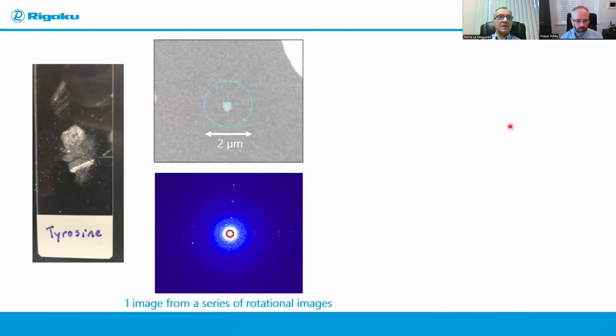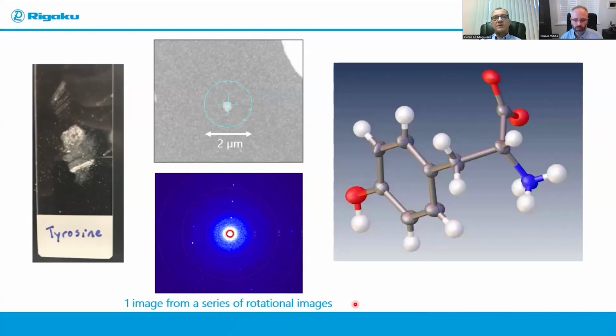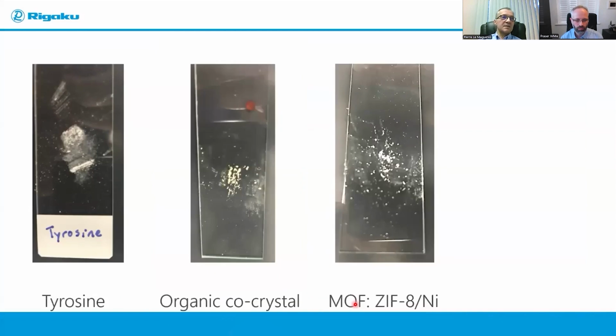Here is a diffraction image that we got from that particle. Now, as I mentioned at the bottom of the screen, this is only one image from a series of rotational images that we got throughout the data collection. Indeed, the grid and therefore the crystal is rotated in the electron beam. So you get many diffraction images throughout the rotation range, and this is just one of those many images. And here is the crystal structure that we got from that submicron particle. So this was the example for tyrosine.